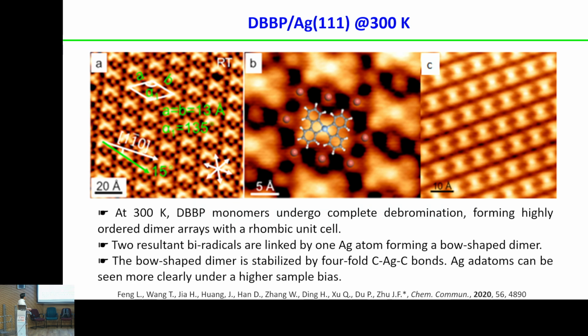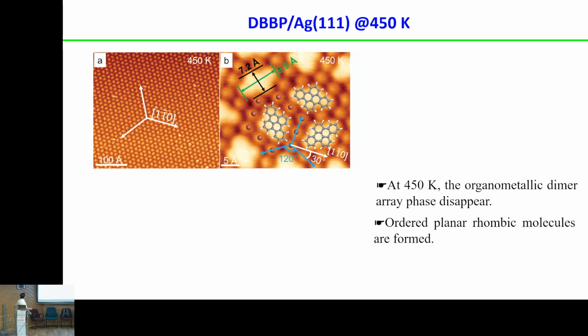What happens if you look with STM? At room temperature, you can see an array of dimers, and these dimers are linked by this four-fold carbon-silver-carbon bond, and these are the debrominated bromine atoms here. So this is room temperature; you see the reaction already starts. Then if you further increase it to 450, all of the organometallic dimers disappeared. So now you form these rhombic shaped molecules. If you zoom in, you can see this forms basically like a graphene nanosheet on the surface.